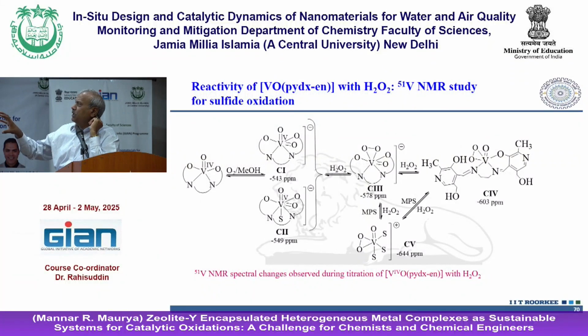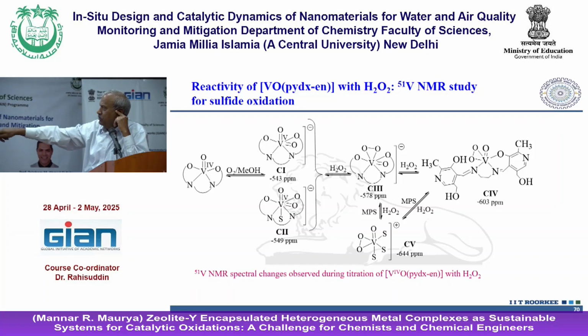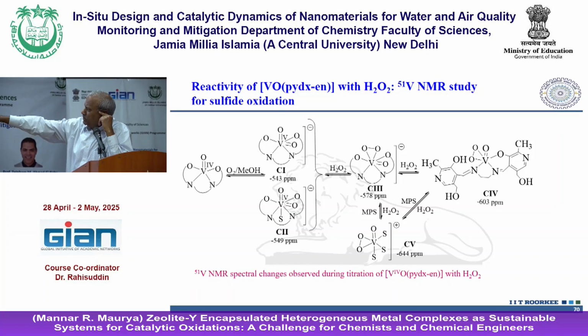This is also theoretically predicted through DFT calculation, where the 51V NMR is possible. You can see that, and it is predicted that in the same way the monooxo goes to dioxo, vanadium 4 to vanadium 5, then 5 goes to the peroxo, and then the peroxo, when you add methyl phenyl sulfide, reacts. When you have excess peroxo, it can go to the ligand-free metal complex and can go back. When you add sulfide, it can go to the peroxo, and if there is not an excess of hydrogen peroxide, then it can convert back to the dioxo. So the mechanism can be given.